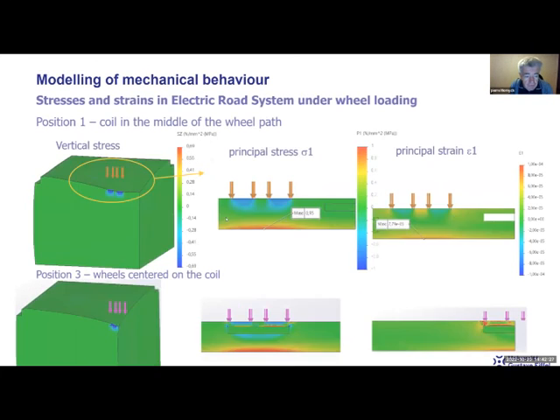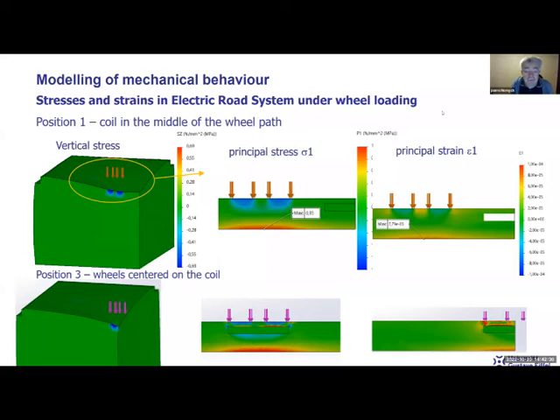And so here you have some examples of calculated stresses and strains. We look mainly at maximum principal stresses, maximum principal tensile strains. So here in the first case, the coil block is here and the loads are applied on both sides. It means it's the normal position of the vehicle when the block is in the middle of the lane. And you can see that in this case, the load is far enough from the coil and there is practically no influence of the coil on the behavior of the pavement. You get normal behavior of the asphalt pavement with maximum tensile strains here at the bottom of the asphalt layer.